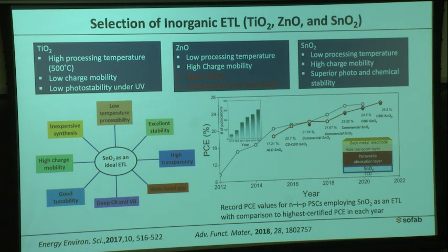Perovskite material is sensitive. It undergoes degradation in the presence of high temperature and polar solvent. Tin oxide dispersion is stable in water, and we cannot deposit any water-based solution on the perovskite, as it undergoes degradation. Another problem is that if we heat the perovskite to a higher temperature, it also undergoes degradation.